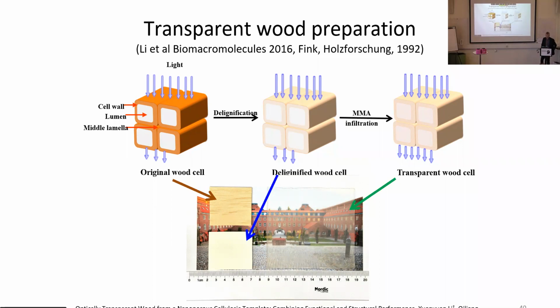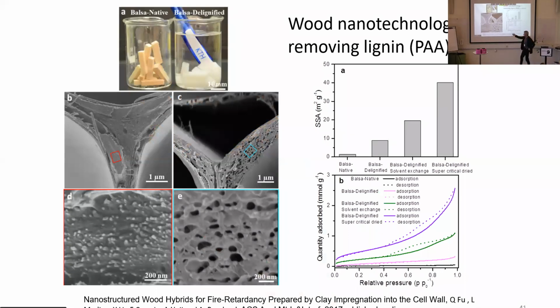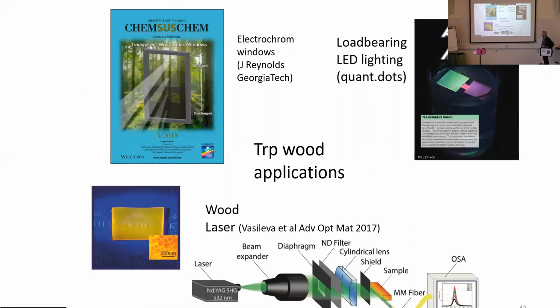And so now there are something like 10 people working on this, funded by the European Research Council. And we're doing all kinds of strange things. But the key is really that we're using a similar method as Fredrik was describing. So instead of having this cell wall with the cellulose fibrils, we create nanoscale porosity, which we can functionalize by different means. We can add dyes, we can add ionic particles, we can impregnate with polymers, and thus we can create completely new materials. And we've played around with this together with colleagues in Kista from a photonics group led by Sergei Popov. One application is we envision that you have load-bearing wood panels in the ceiling, and they are LED panels. So we use quantum dots for lighting.